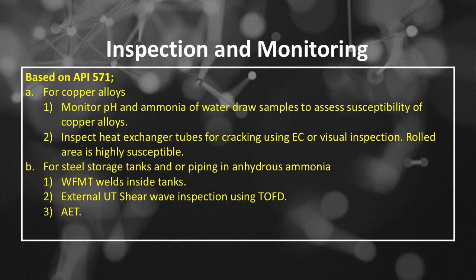Ammonia stress corrosion cracking damage inspection and monitoring based on API 571. Number A, for copper alloys. Number 1, monitor pH and ammonia of water, draw samples to assess susceptibility of copper alloys. Number 2, inspect heat exchanger tubes for cracking using EC or visual inspection. Rolled area is highly susceptible. Number B, for steel storage tanks and/or piping in anhydrous ammonia. Number 1, WFMT welds inside tanks. Number 2, external UT shear wave inspection using TOFD.